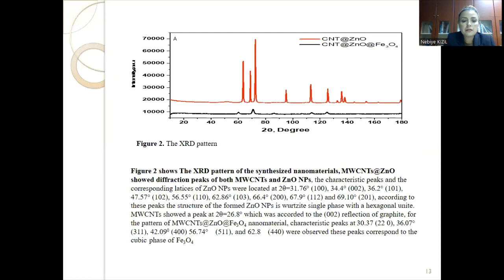This is figure two, the XRD pattern. The figure shows that the XRD pattern of the synthesized nanomaterials showed diffraction peaks of both multiwall carbon nanotubes, zinc oxide and magnetic nanomaterials peaks.